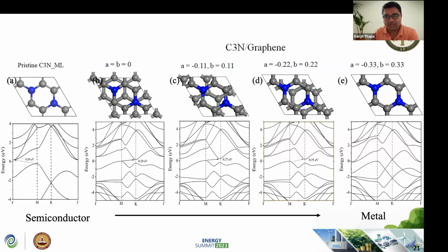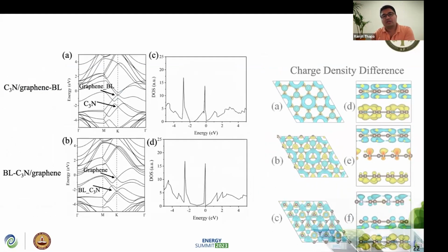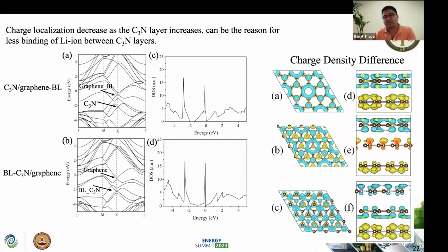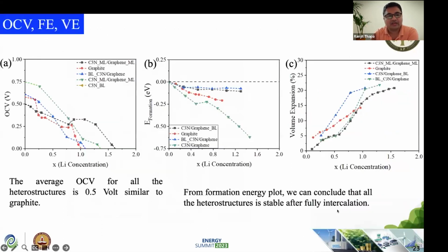And then we have done all the same calculations what we have done in the previous work, and then we have identified how the two layers' charge density difference or the localized delocalization, because graphene is mostly delocalized, but wherever C3N has a nitrogen bond, nitrogen has a localized, I will say, lone pair electron, which will really create sometimes repulsion or attraction depending upon the type of molecule it is interacting with. So in this way we have formed different types of anode materials, and again we have calculated OCV, and you can see that OCV you can really make it very well, particularly for this red one or this blue one, and even for the black one where C3N monolayer and one graphene layer.